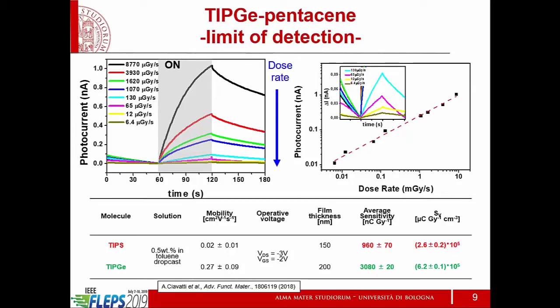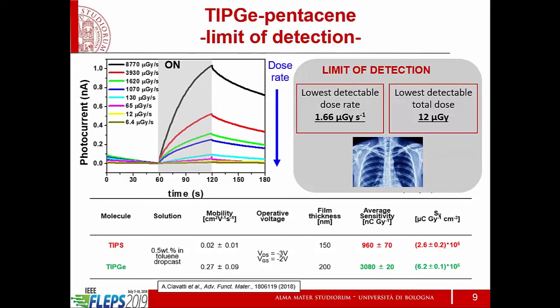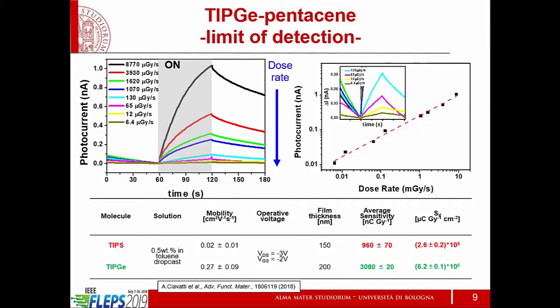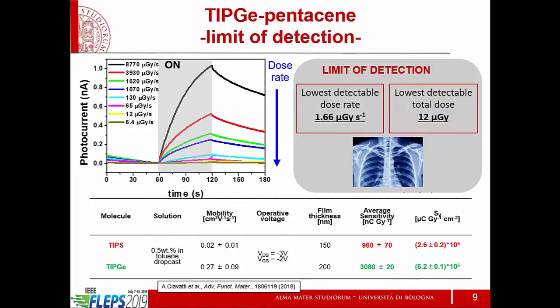So how do we measure the limit of detection? We decrease the dose rate, and we measure basically what is the minimum detectable signal that we can reliably and reproducibly obtain. And the message is that we get a very good limit of detection that is reported here, which is extrapolated from this curve. You see, this is again the dose rate going down. And the lowest detectable dose rate is 1.66 micrograys per second, which is less than the required or standard dose rate delivered in a standard X-ray diagnostic scan. So we're not talking about devices that are so far in terms of performance with respect to those that are routinely used in medical applications.